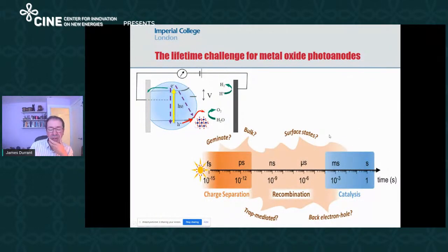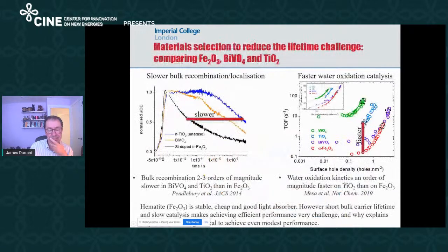To give you another way of thinking about the kinetic challenge, this just illustrates the idea that the charges are generated on very fast timescales, the catalysis is slow, and between those two timescales there are many loss pathways: traps, surface states, bulk recombination. All of these processes, on timescales going from picoseconds to milliseconds, mean that most of the carriers which are generated by the light do not drive catalysis. And that, of course, is the challenge.